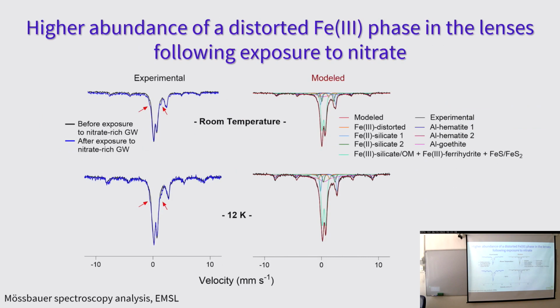So looking into solid phase iron, we use Mossbauer spectroscopy, which is, again, a really fabulous tool because it teaches us about the oxidation state of iron and the various species of iron that are present in our sample. So here on the left-hand side, we have the experimental data. This is only for the fine-grained lenses. So we have the experimental data before and after exposure to nitrate, which means that we have just the fine-grained lenses before the experiment, that's the before, and then after the entire experiment, so after the exposure to nitrate.